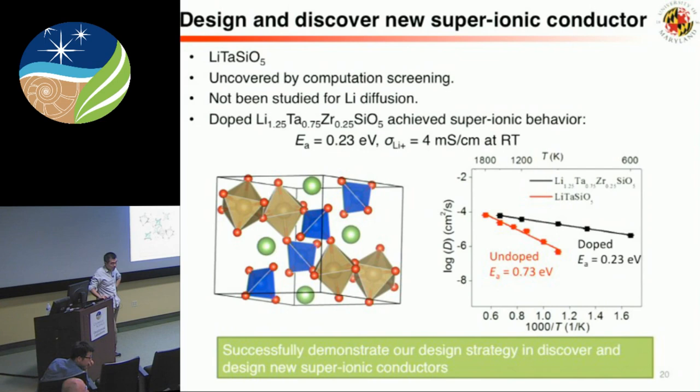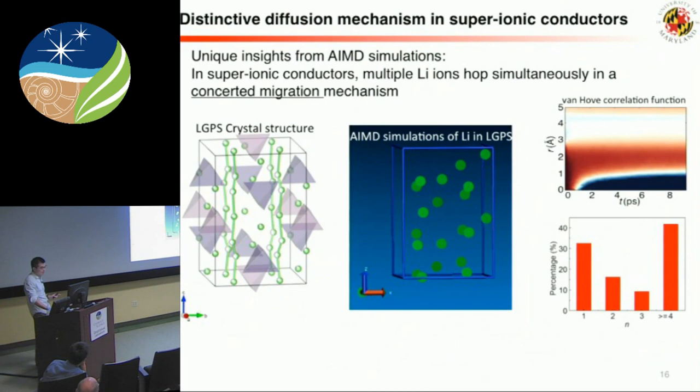Okay, are there any questions so far? Yeah? So when you look at this LGPS, it's highly anisotropic. In one of our papers we explain it in detail. Basically, they diffuse much faster along this C channel. In the AB direction there is also some diffusion, as you can see, but it's much, much slower. It has higher activation energy.